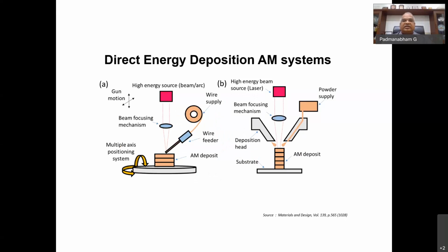The other technique is the direct energy deposition technique. In this one, what you do is you have a heat source, you have a substrate on which you are building the component. Into the heat source, you feed the feedstock material either in the form of a wire or powder, and the heat source will melt it, and the droplets formed will get deposited on the substrate.